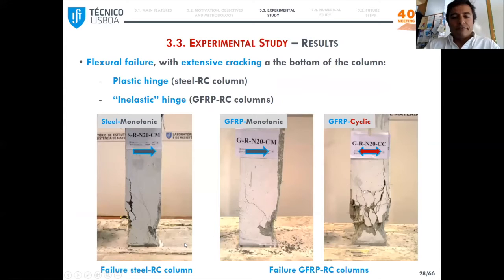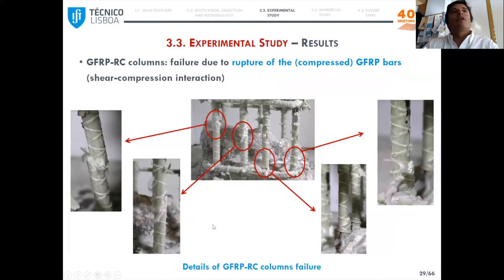So in terms of failure modes, as expected, all columns failed due to flexure, with extensive cracking next to the bottom of the columns and formation of a plastic hinge in the steel RC column and what we call an inelastic hinge in GFRP reinforced concrete columns. In these cases, failure occurred actually in the GFRP bars, as you can see here in these photos, due to compression and possibly with some influence of shear.